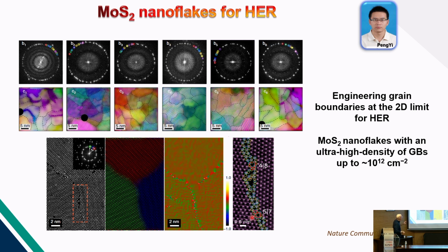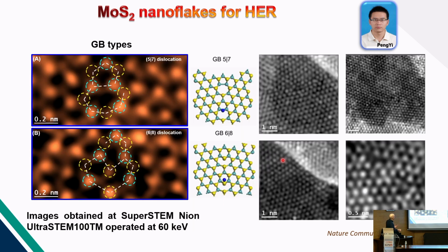So the idea in this work was creating many grain boundaries, because at the grain boundary, you see that the coordination of the atoms is not the same as in the basal planes. You have many defects, and these defects create a lot of dangling bonds, which are really avid for the molecules of water. So what they will be waiting is for the molecule of water to separate it and break it. So that was the main idea here.